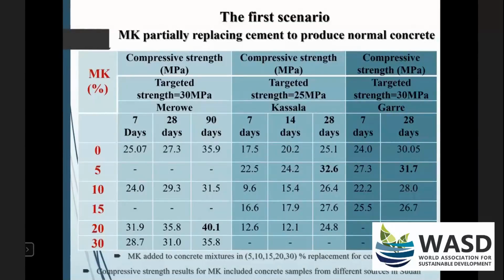And we checked after that the compressive strength. We checked the compressive strength for the different samples at different curing ages. For the first sample, we had it for 7 days, 28 days, and we even studied the long-term effect of this material in our mix. And we were able to get results exceeding the targeted strength for the first sample. As for the second sample, or the first design, we had 7, 14, and 28 days, and we were also able to get compressive strength matching the required or even higher than the targeted strength. The same applied for the last sample from another location, and it gave us the same results.